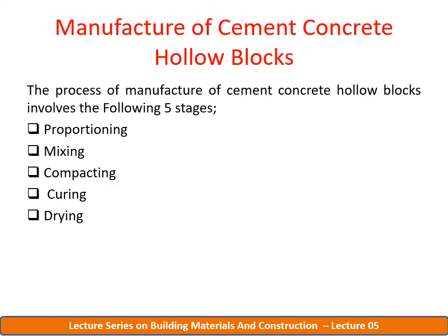Compacting. In the case of compacting, the purpose of compacting is to fill all the air pockets with concrete as a whole without movement of free water through the concrete. Excessive compaction would result in the formation of water pockets or layers with a high water content and poor quality of the product.